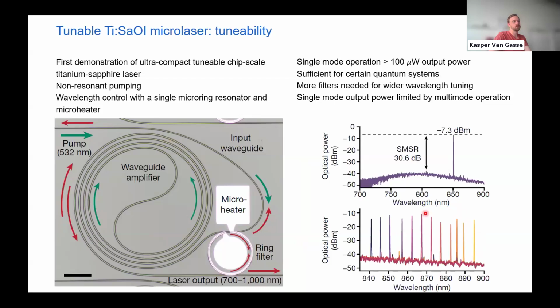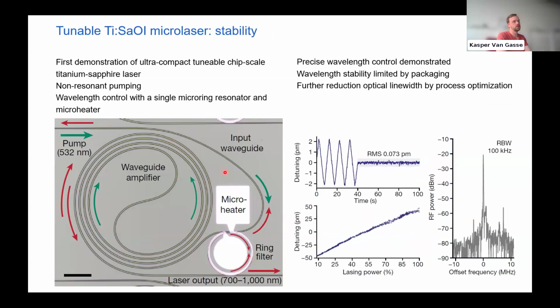It's very widely tunable. This is, I forgot by heart, a few tens of terahertz. It's very hard to achieve actually with other gain media. And this is still only a fraction of what would be achievable. Even with a simple cavity and very short cavity length, we can already get line widths on the order of 100 kilohertz. And I think we can do much better than this.